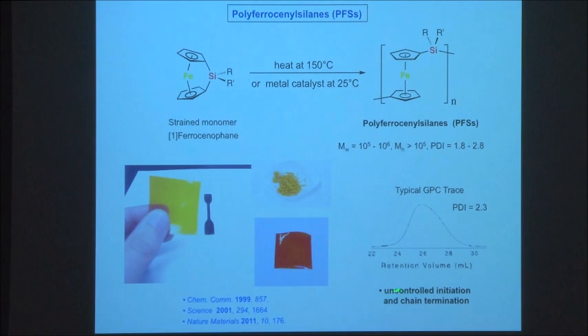So you get uncontrolled chain termination. You also have an initiation step that's uncontrolled. In each of these processes, the initiation is a slow process, and so chains start to grow at different instants. And this will also lead to different chain lengths, which broaden the distribution. But you can get high molecular weight materials, as you can see here, which can be processed just like organic polymers.